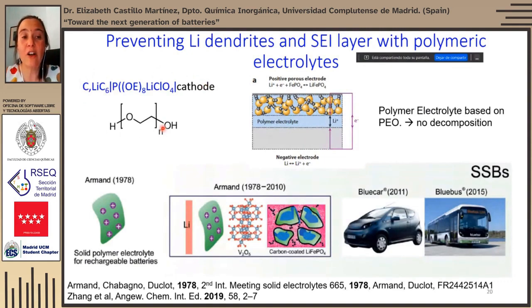And to make the contact between the cathode and the polymer electrolyte with less interfacial resistance, and to help the lithium ion charge transfer, typically the polymer electrolyte and the cathode are mixed on the cathode side. There is, of course, then a layer of polymer electrolyte free from the cathode. And the good thing of this polymer electrolyte is that there is no decomposition, so no SEI layer formation.